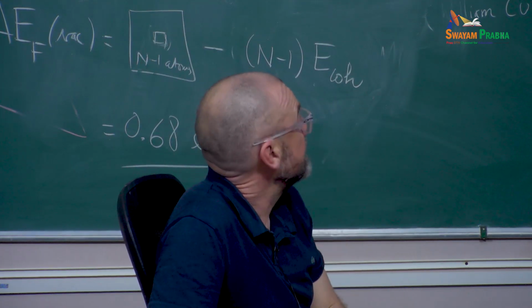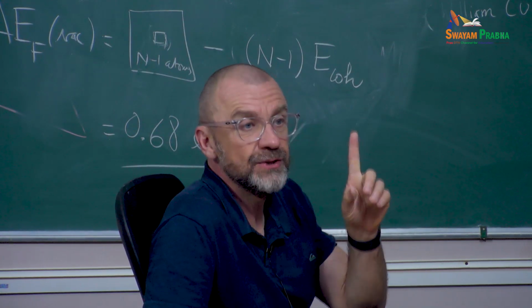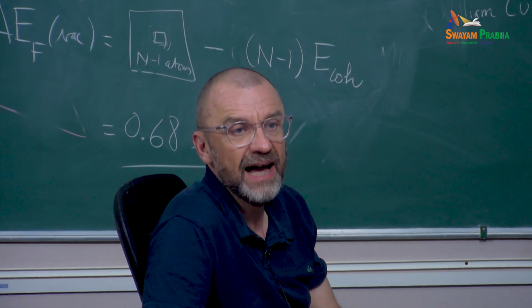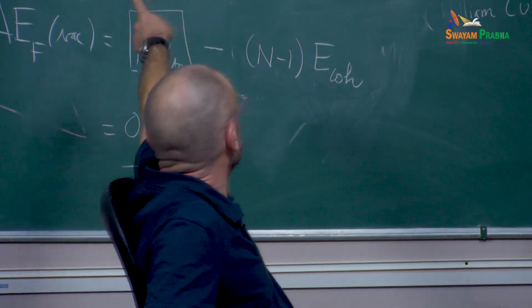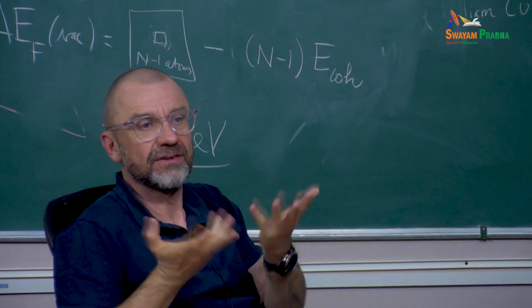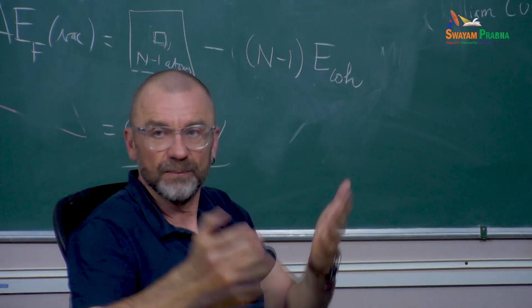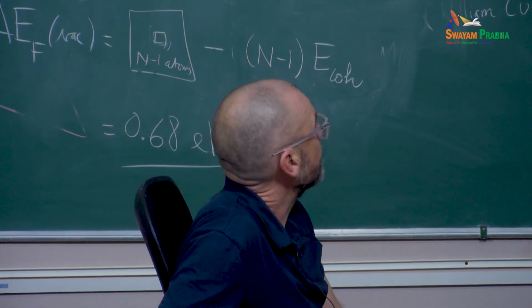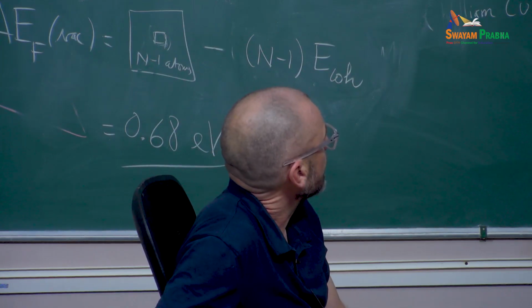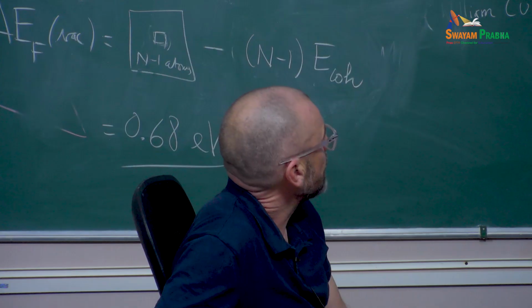The size, yes. Instead of having just one unit cell, now I have 4 unit cells in X, Y, and Z. This is because if I have just one unit cell and I remove one atom, the number I'm going to get is going to be completely crap, right? So 4 is just a number, small but different from 1. So I create a perfect crystal.